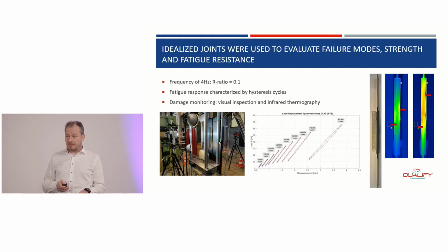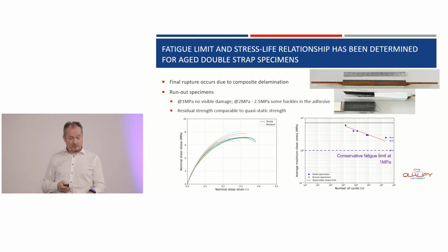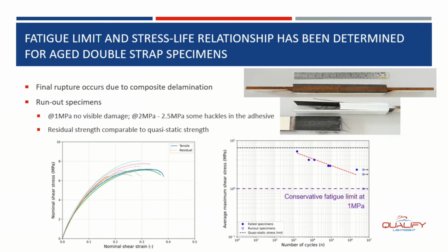If we look at the properties themselves at the end, so we did quite a lot of series of these fatigue tests, and if I look at the fatigue properties of aged specimens, so again, aged in the salt spray aging, 6 weeks, 35 degrees, 50% relative humidity and 5% of salinity, you see the specimen at the top right, so you see the nice brown oxidized color.